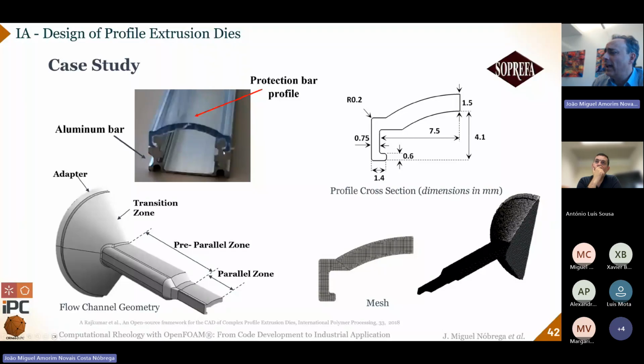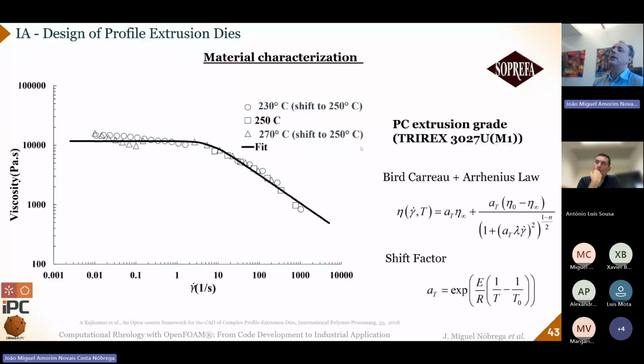But Soprefa was trying to manufacture this profile, a lead covering profile, and they were not able to do it by using a traditional approach, by trial and error experimentally, because the profile has different thicknesses, as I mentioned: 1.2 millimeters, 0.6 millimeters, 0.75 millimeters, and they didn't manage. So we used the code.